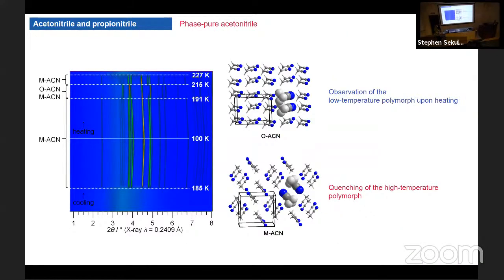Let's first talk about pure acetonitrile. These two phases have been known for decades now. What we notice, and it's quite interesting, is that when we cool down the system, we have quenching of the monoclinic high temperature phase. So what happens is, we would expect when we cool down to have first the high temperature form, which is monoclinic, and then a phase transformation into the orthorhombic low temperature form. We do not see that.